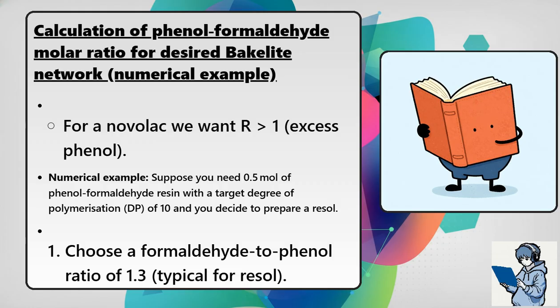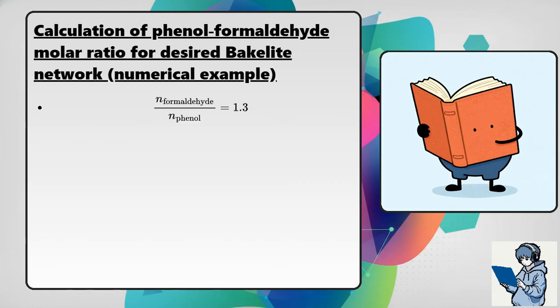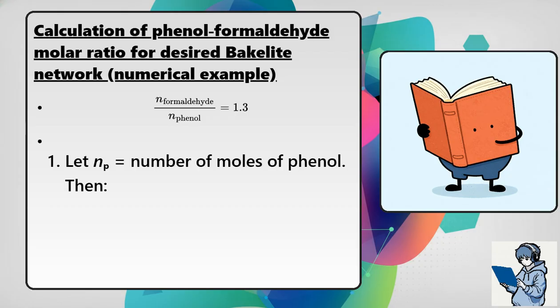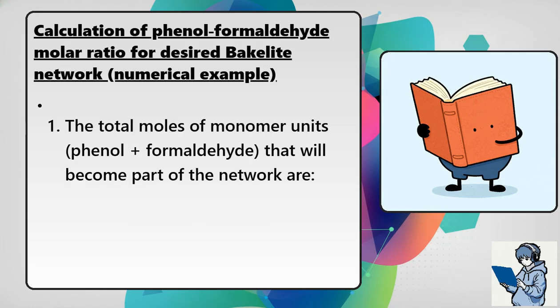Step 1. Choose a formaldehyde to phenol ratio of 1.3, typical for Resol. N formaldehyde divided by N phenol equals 1.3. Step 2. Let N phenol equal number of moles of phenol, then N formaldehyde equals 1.3 times N phenol. Step 3. The total moles of monomer units, phenol plus formaldehyde, that will become part of the network are N total equals N phenol plus N formaldehyde equals N phenol times (1 plus 1.3) equals 2.3 N phenol.